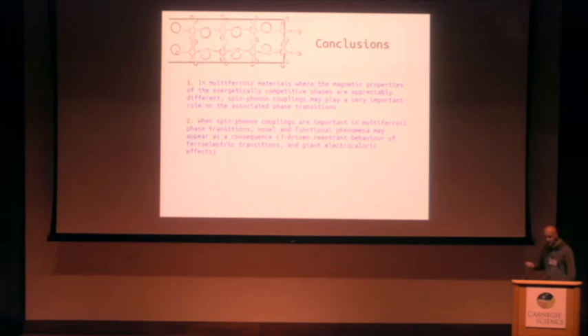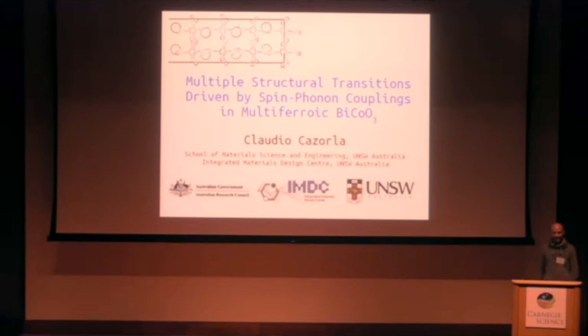As a result of the effect of these spin-phonon couplings, we can find very impressive functional phenomena, for instance, temperature-driven reentrant behavior and giant electrocaloric effects. And we believe that bismuth cobaltite is a good candidate in which to realize all these effects, by making solid solutions with iron or lanthanum, or by growing thin films. So thanks a lot for your attention.